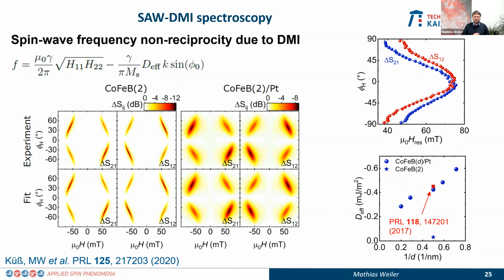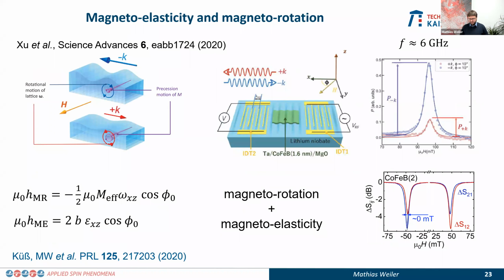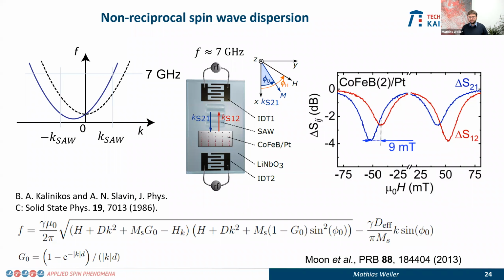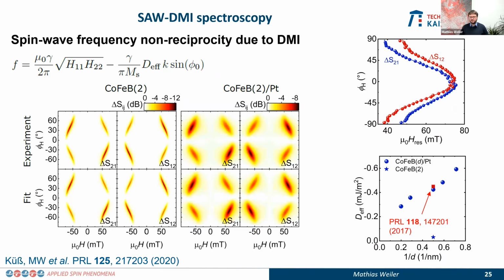Okay? So that could already help to increase the non-reciprocity, but the non-reciprocity here that we observe in total is still rather weak. It's not technologically useful. It's a couple of dB. So we basically went from a non-reciprocity of about 1 dB to one that is a bit less or a bit more than 2 dB. That's kind of nice, but not useful. Okay.